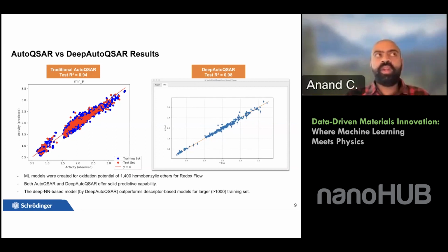Based on internal case studies, we see that once you have more than around 500 data points, there's a strong likelihood that a deep learning approach is going to benefit your particular application. And with DeepAutoQSAR, you can actually train on a GPU to make the training even faster. This model was trained for 4 hours on a GPU to get this particular performance.